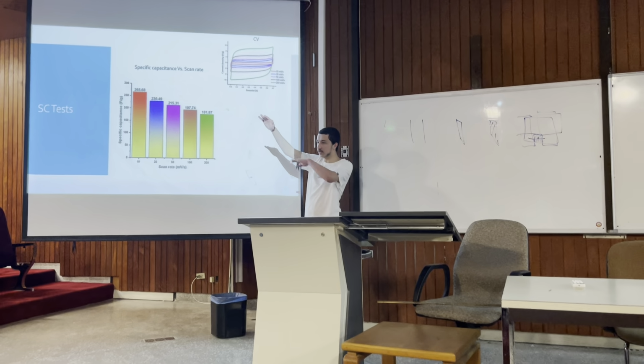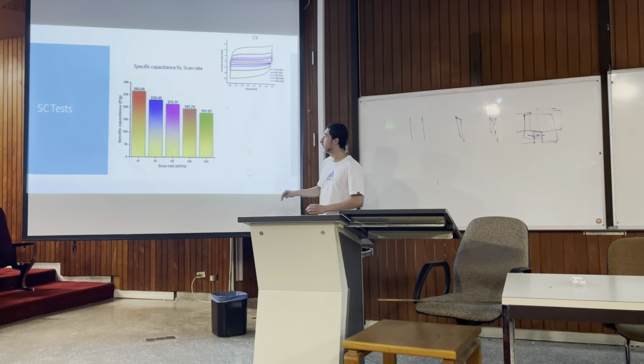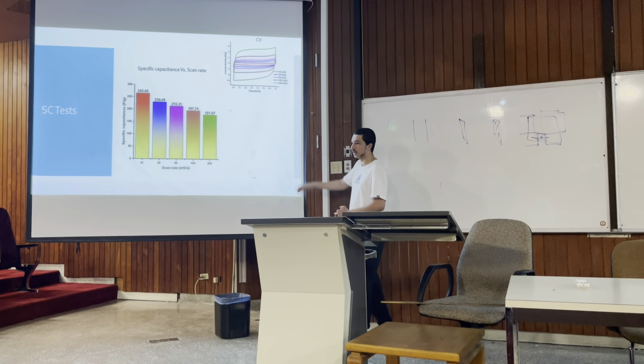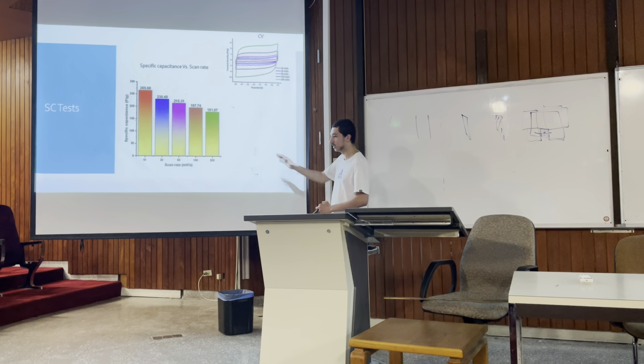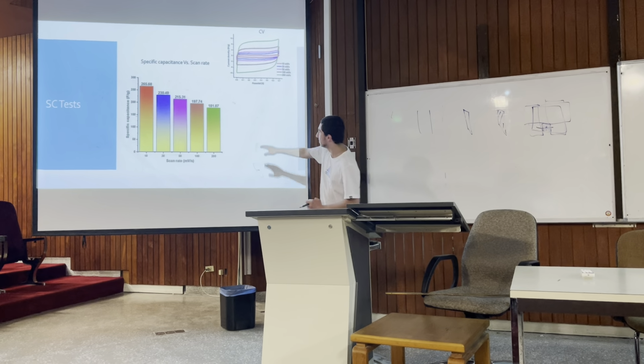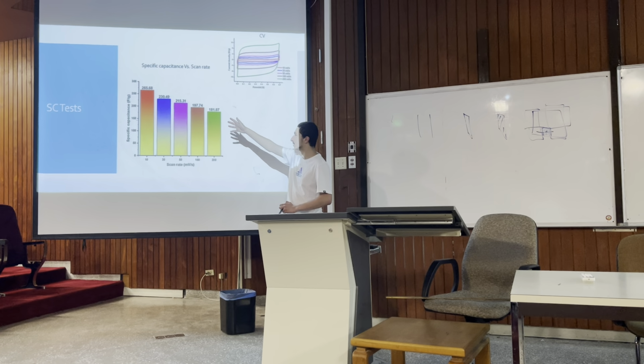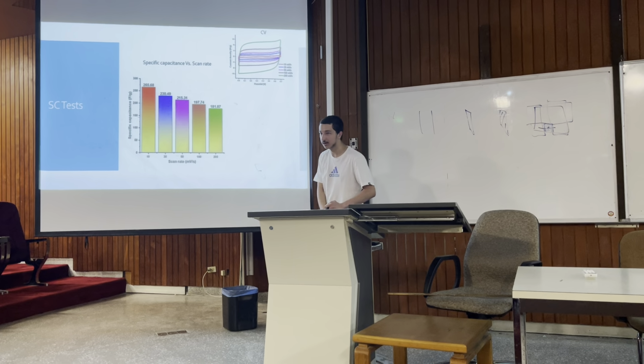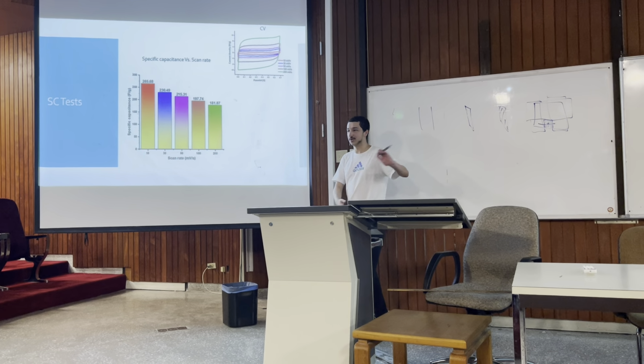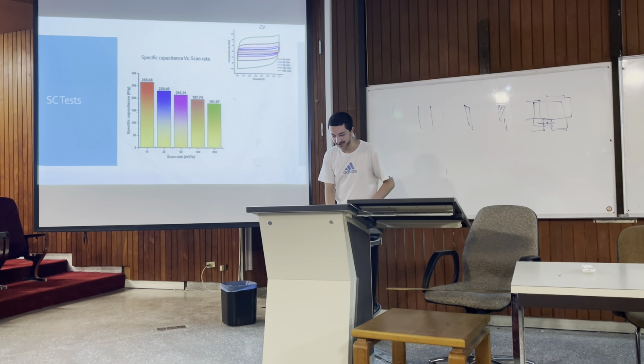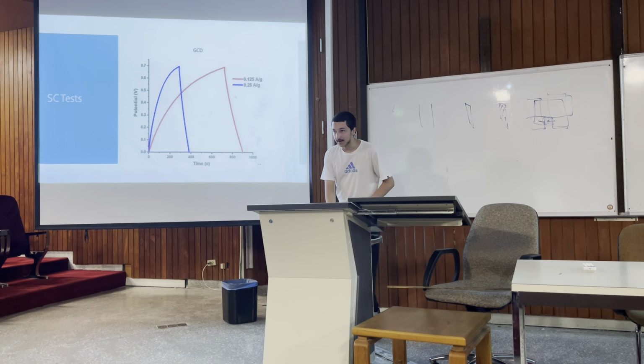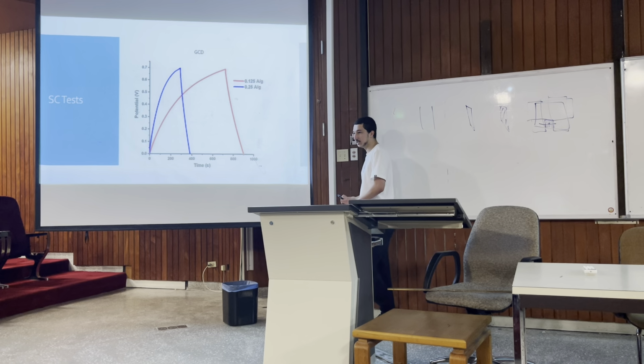So for the same potential window, we have area over the scanning. And so we get, let's say, a negative 1 relationship, which is what we expect, which is good. And also, as we can see, the specific capacitance here is 200 and something, 180 something, as opposed to picofarads or nanofarads. So it's very, very significant. Farad, yeah. This is GCD, charge discharge.